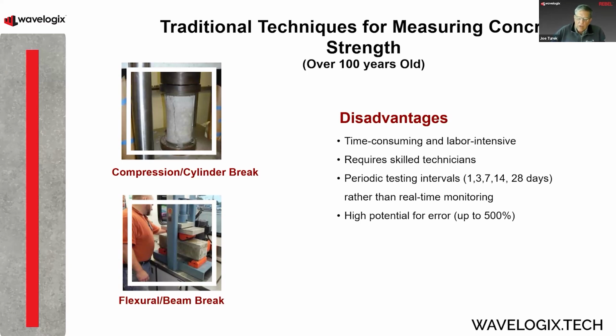Well, the 100-year-old technology has been to use a companion cylinder or companion beam. And then we take those cylinders at periodic intervals: 1 day, 3 days, 7 days, 14 days, 28 days. We crush those cylinders and we determine what that strength is at that particular time. And unfortunately, it's not real time.